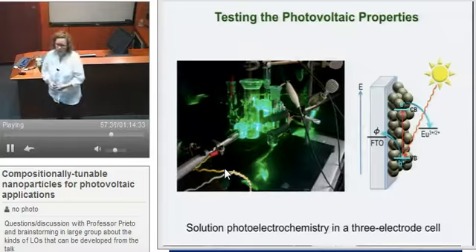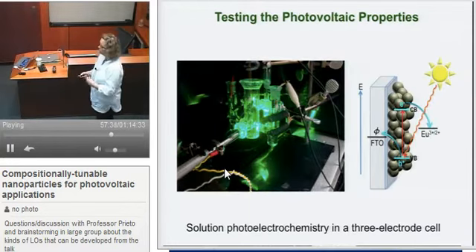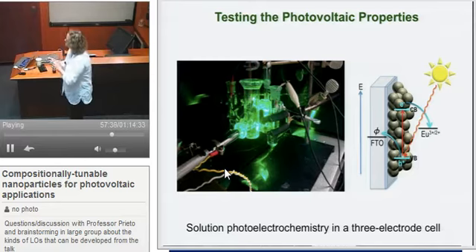Now, we don't build full solar cells, we do photoelectrochemistry because it's much simpler and we only have to deal with one interface. So here's the idea. I know you guys saw valence bands and conduction bands yesterday. So to simplify, this is the top of the valence band, this is the bottom of the conduction band. What we're going to do is use light to excite an electron and create an electron-hole pair. This compound is a p-type semiconductor, so we want to collect the holes. So we're going to sweep our electrode to negative potentials, and so the holes are going to go into the electrode. But now we're left with these electrons, and we need to do something with them.